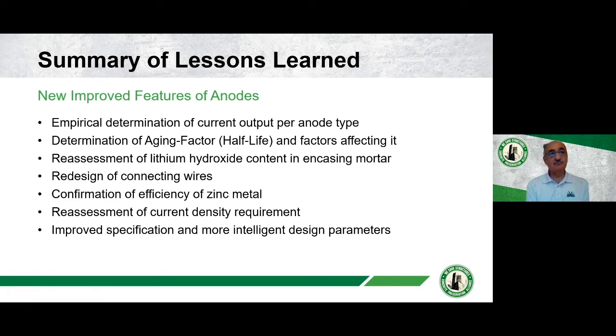And we reassessed the current density requirements. From the standard, we assume that you need a current density of 0.2 to 2 milliamps per meter squared if you're trying to prevent corrosion. I'm now saying maybe we need 0.4, and maybe the standards should be updated to that. And from everything that we learned, we can now have improved specifications and more intelligent design parameters. We can design in a better way, having better knowledge of how our anodes are actually working.